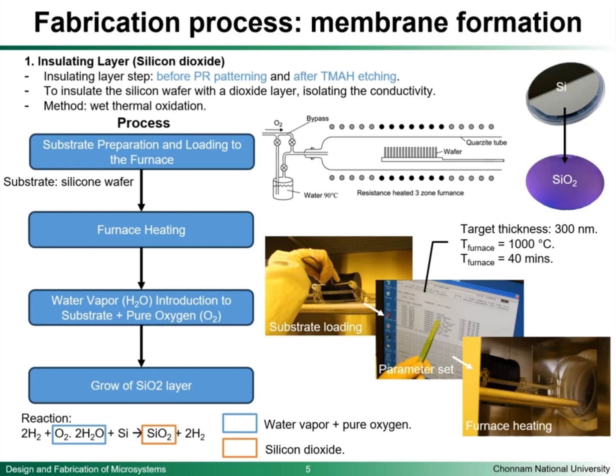And the purpose is to isolate the silicon wafer with the extra layers, so we are isolating the conductivity of the silicon wafer. And then the process itself: first we have to prepare our silicon wafer, and we load it into the chamber of the furnace, and then we set the parameters, utilizing 1000 degrees Celsius in the furnace with a heating time of 40 minutes because we want to achieve a target thickness of 300 nanometers.